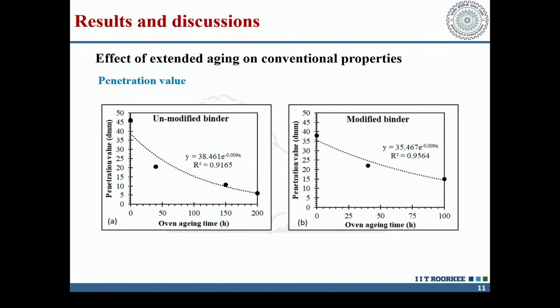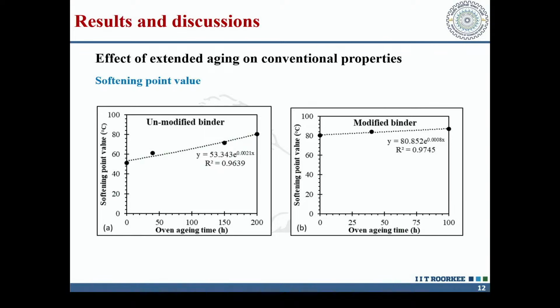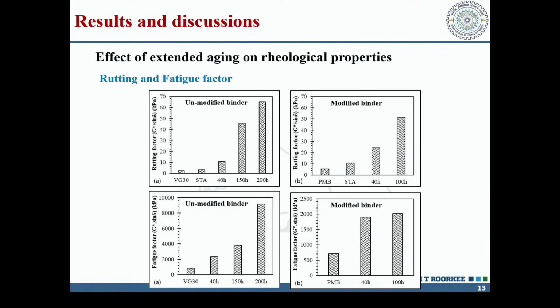The plot is of DSR. You can see here how the penetration value is varying. The variation is exponential, you can see here, and it is almost the same in unmodified and modified binder. For the softening point, it is not exponential, it is rather linear. You can see here the effect is also the same in both. Then we have tried to find out the effect of extended aging on rheological properties.